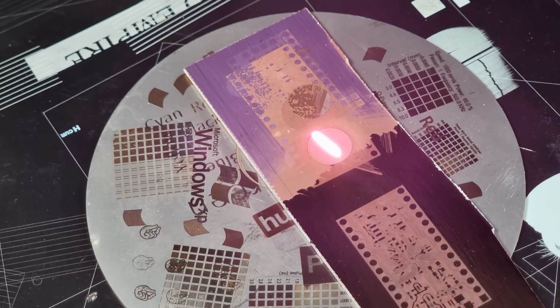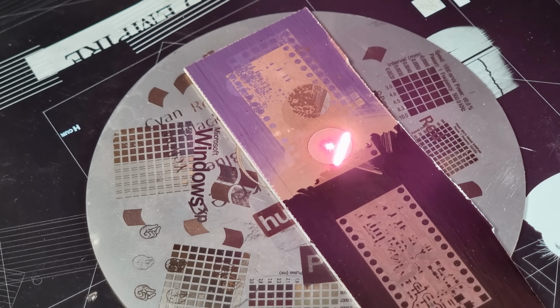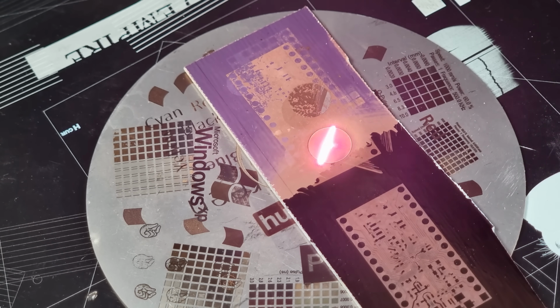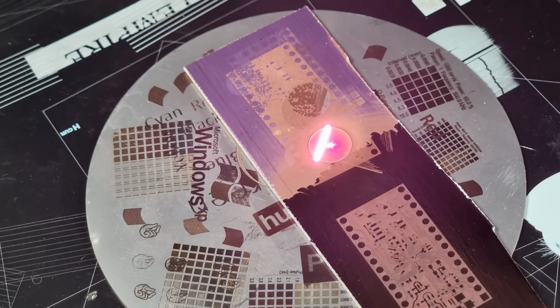If it triggers the population inversion with a larger seed impulse, of course the amplified outgoing pulse will also be taller. TLDR, for maximum impact on our smooth copper surface, I would choose a 20 nanosecond pulse width at the lower end of the frequency range, so that we don't dump unnecessary heat into the workpiece. And yeah, that started to do something after a few minutes.